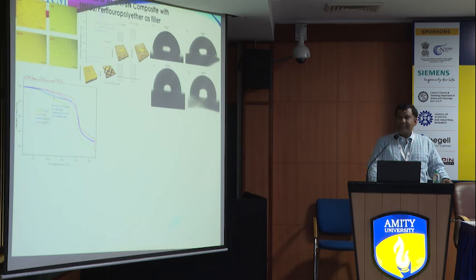Thermal stability also improves a lot after adding the liquid filler, approximately 100 degrees from the pure SU8. And coefficient of friction also, you can see here, at 2 Newton load we can achieve 0.1. Okay, but it will not fail. So what we do is further increase the load until it fails. At 4 Newton it further does not fail, and friction is also not increased that much, it is steady state, but at 6 Newton load it fails. So that was the maximum load, meaning 4 Newton is the critical load.